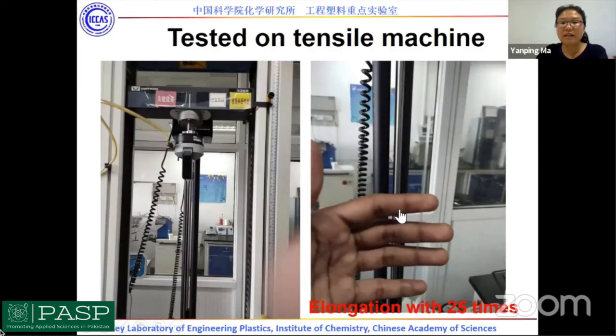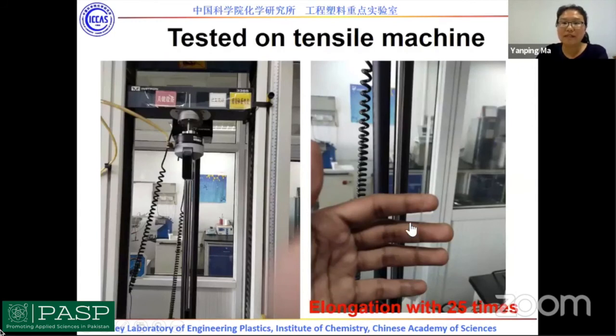You can see clearly here. From this photo, we put our sample in the tensile machine. Initially, it is just a small sample here. When we elongate it to 25 times, it hasn't broken. So it indicates that the elastomer properties are good.